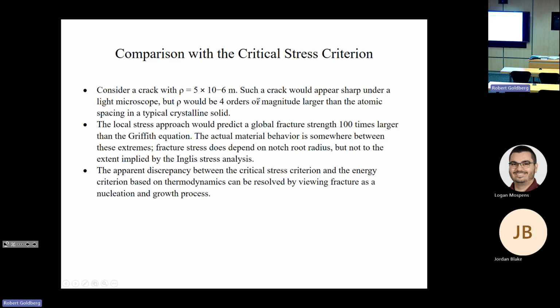A crack like this, if you looked at it under a microscope, would appear to be very sharp. I mean, 5 times 10 to the negative 6 is a pretty small radius of curvature. It's about a 200th of a millimeter. However, this radius of curvature is still 4 orders of magnitude larger than the atomic spacing in a typical crystalline solid. So if you use the Inglis type of approach, you'd predict a fracture strength that's 100 times larger than the Griffith equation.